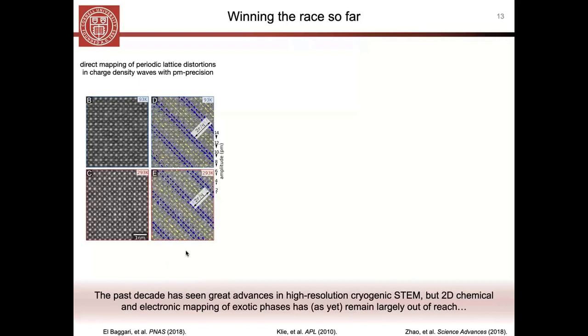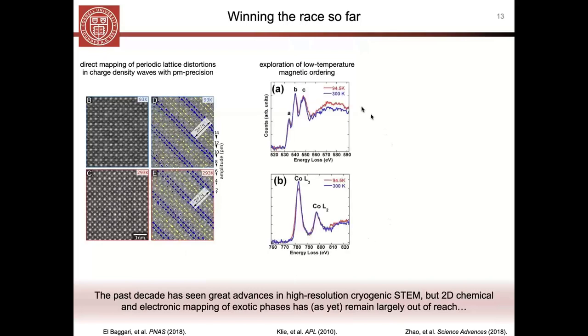Using very high resolution STEM, there's been some cool work mapping, with very high precision, the subtle lattice distortions in different quantum materials and different phases. And on the EELS end of things, you can, for instance, just sum while the beam is scanning. Here it's STEM, but we've lost the 2D atomic localization, though we can still probe the local region and do cryo EELS. There's work showing subtle changes in the fine structure of the edges as you cross phase transitions.